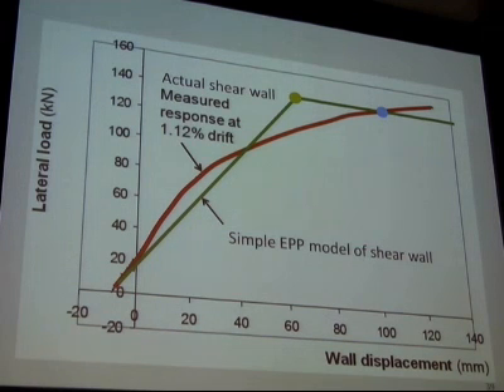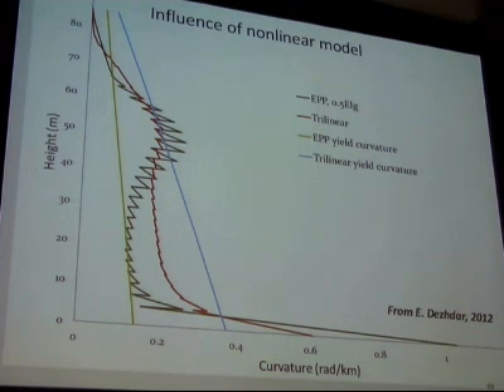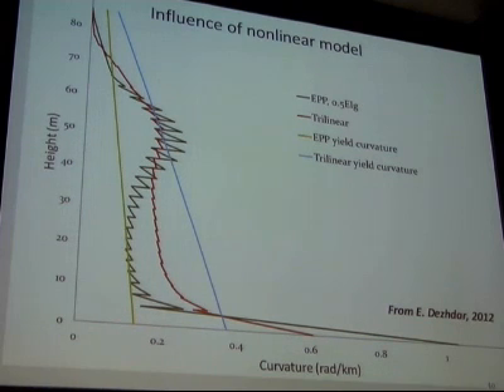If you use that model to analyze the walls, and this comes from some of the Sands work, suddenly the problem really goes away. What I'm looking at here in this diagram is the yellow line, the yield curvature for an elastic plastic model, and the dark green line, the predicted curvature demands from that model. So you've got curvature demands much greater than the yield curvature from that model. But if you use the trilinear model, first of all, your curvature demands are the red line. They've reduced slightly, but much more importantly, the yield curvature has gone up a lot. So by switching to a more accurate model, the problem, in my opinion, essentially goes away.